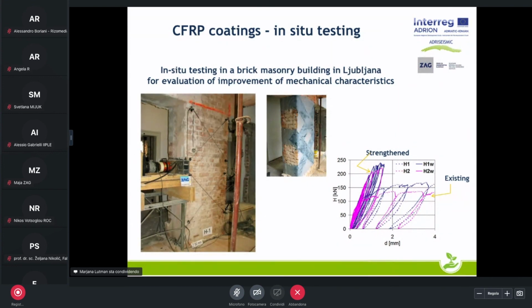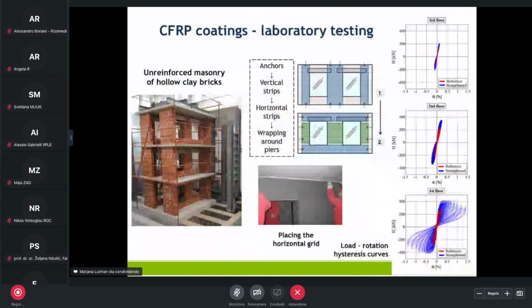of this measure. Two specimens were tested, first in original condition and then strengthened with carbon fiber strips, which fully wrapped the wall. And as seen from the diagram here, this measure improved the lateral capacity of the wall by up to 60%, but it is important that it reduced the deformation capacity by more than 3 times. Therefore, it is important that such a measure is placed on all walls in the building in order to prevent spoiling the original regularity of the structure.